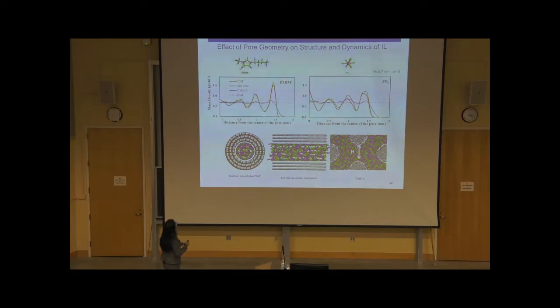The next effect I considered is pore geometry. There are different kinds of nanoporous materials available out there. So I considered three different types of nanoporous material: carbon nanotube, slit graphitic pores, and a CMK3 model. I still observed a significant layering in CMK3 and slit pore, but in the CMK3 model, where the gray ones are the carbon and this is the ionic liquid, these pores behave more like a bulk liquid, and there is no significant interaction between these pore walls and the ions confined inside it. And we observe that that mainly happens because of the surface roughness of the CMK3 model, which does not allow ions to strongly bind with the surface, and that's one of the reasons why the capacitance is not very high.